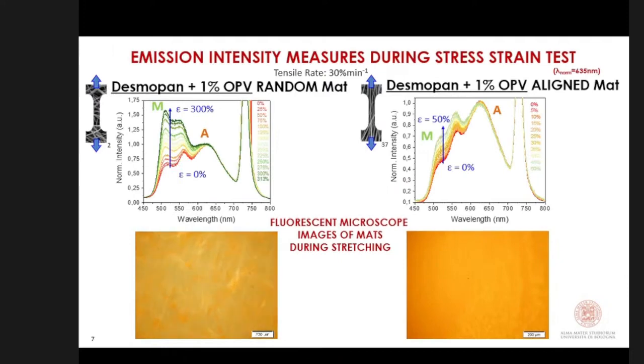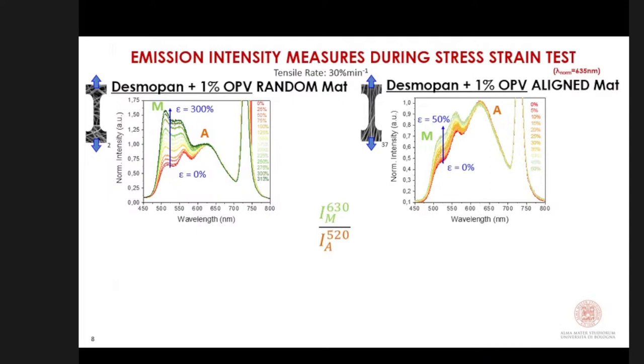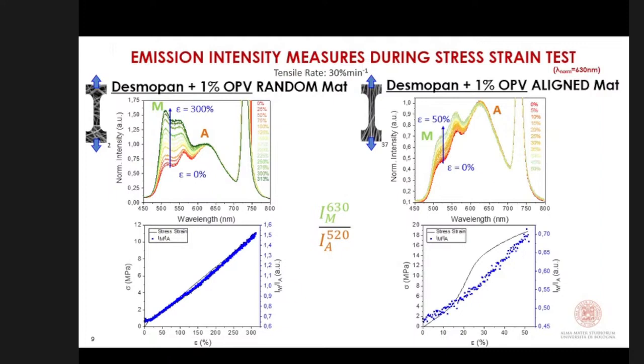As you can see here, with increasing strain, the intensity of the monomer band increases in both cases. So we pass from the orange emission color characteristic of the aggregate to the green one characteristic of the monomer. And this color transition could be observed in both samples. Then we exploit the wavelengths, the one of the aggregate and the one of the monomer, and we calculate the ratio between the two intensities. With this ratio, we investigate how it varies with increasing strain, and we observed that the ratio increased linearly with the strain in both cases.